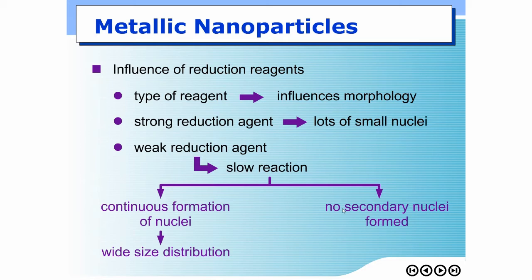It is possible to get supersaturation, but we do not have nucleation as long as the energy of the whole solution has not overcome the barrier. In that case, the size of nuclei will not be greater than the critical size or stable size. Okay, in that case, there will be no secondary nucleation.